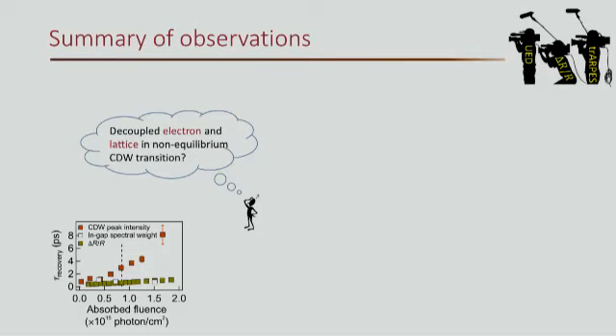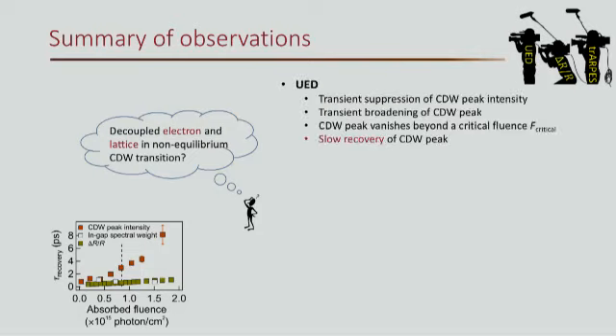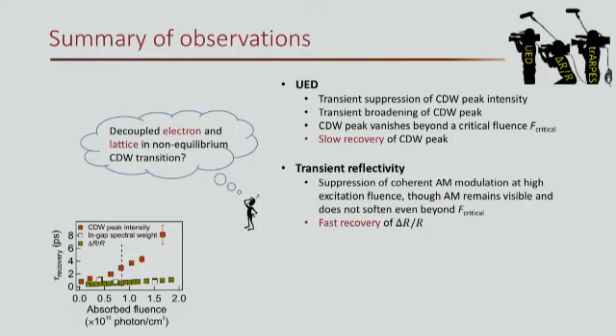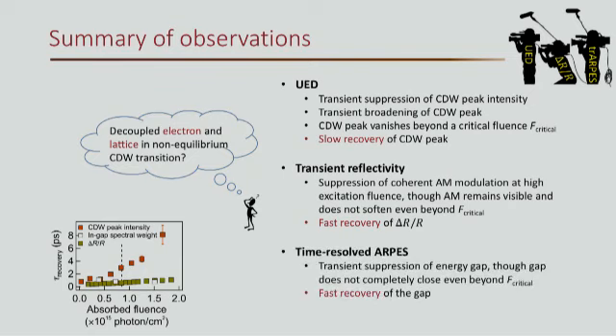Well, let's do a summary of what we have observed so far. From UED, we observed a suppression of the intensities, and there's also a broadening effect. And both are very slow in terms of recovery. In transient reflectivity, we see a suppression of the coherent oscillation of the amplitude mode. But bear in mind that the amplitude mode doesn't really go away even if we pump really hard. And again, it also doesn't soften even beyond a critical fluence where the CDW peak seen in UED is fully melted. And of course, in ARPES, we see a partial suppression of the energy gap. As you see from the previous plot, the gap doesn't really fully close. And again, there's a very fast recovery of the spectral weight inside the gap.